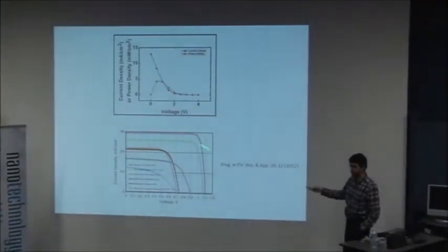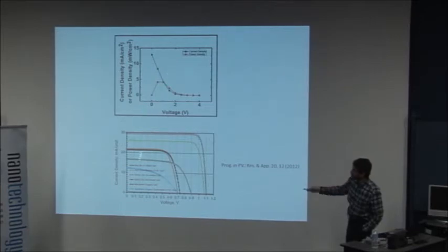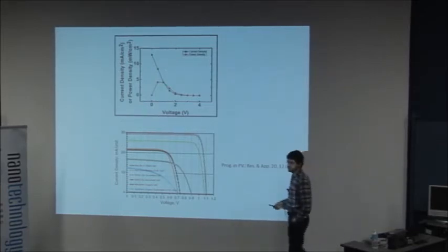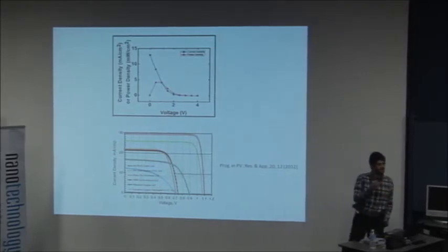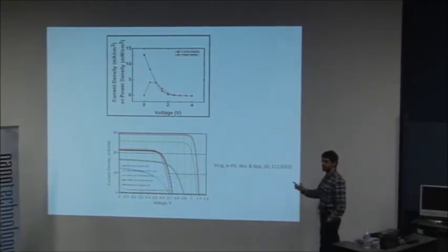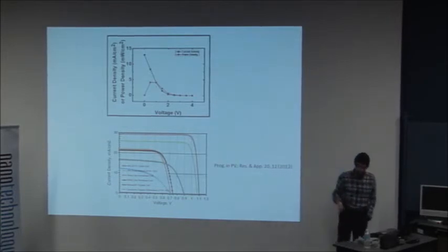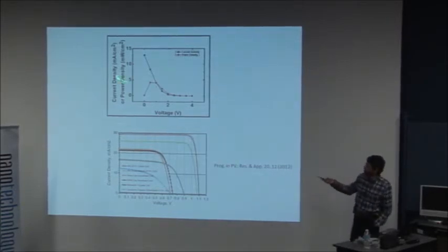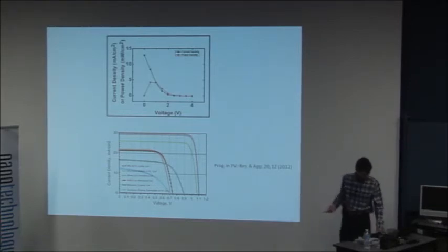of that unit area, you will see that it's already, if you look at these numbers and compare with this, which is from a recent review of photovoltaics. So this is state-of-the-art photovoltaics. You see that the numbers are very comparable with state-of-the-art photovoltaics in terms of power density and current density. And that's something that's very important because it determines cost, right? So even though efficiency is poor, on some of the fronts, it's already quite competitive, even these early prototypes.